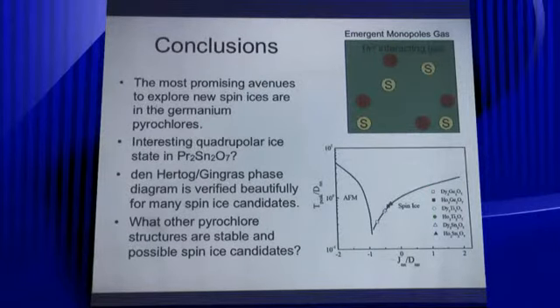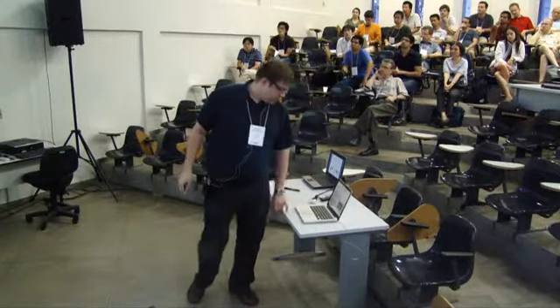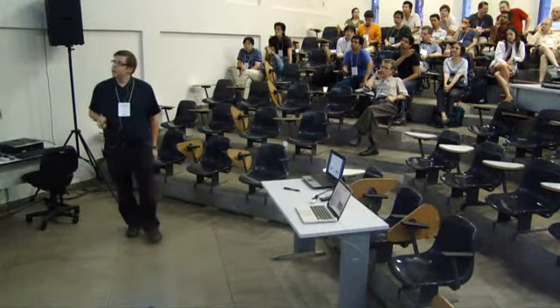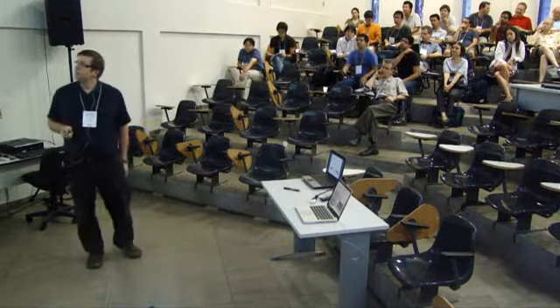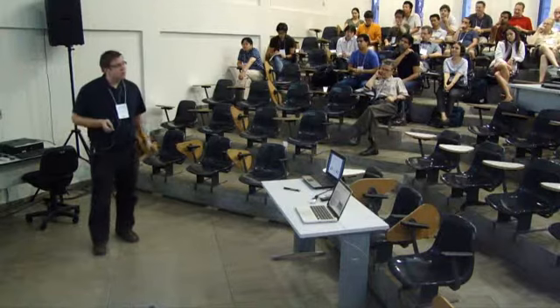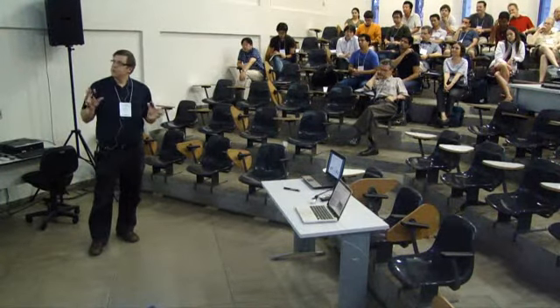Now, where do I think that the chemistry is going in the future for these? Well, there are other candidates you can think of beyond the germanates. And there are lots of groups working on different types of compounds, including us. So you may think about the zirconates and the hafnates, for example. You can make both these samples in pyrochlore form. However, you have to worry about site disorder, right? So the B site and A site are going to be roughly the same size. So you have to make sure you have very good samples.